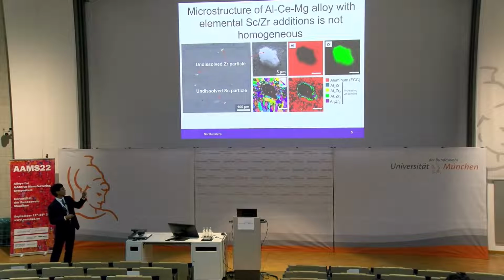We can also take a look at the phase mapping of this aluminum-zirconium interface. And what we see is a series of aluminum-zirconium containing intermetallic phases, where we have these less zirconium-rich phases towards the matrix. As we press closer towards the center of the particle, these phases become more zirconium-rich. And this sort of structure is very characteristic of zirconium diffusing from the zirconium particle into the surrounding liquid aluminum. Now, of course, these particles are quite undesirable, since any scandium or zirconium locked in these particles is therefore unavailable to form secondary precipitates later on during aging, which provides strength.